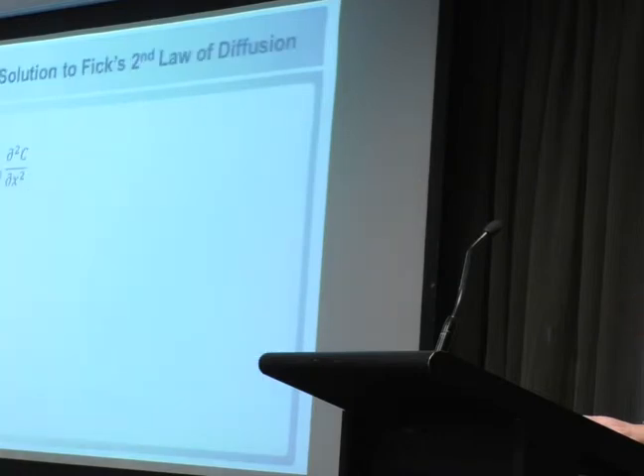Now, most of the models, in fact all of the models, were based on Fick's second law of diffusion, which just says that at any point in your concrete, the flux of chloride ions arriving is proportional to the rate of change of the concentration gradient that's already been established. That explanation probably proves that I'm not a mathematician. I'll prove I'm not a physicist by saying that my intuition of that is it just says that marbles roll fastest down the steepest part of the hill. But the main value of that is that you can obtain a simple analytical solution to that partial differential equation, which is Crank's solution there.